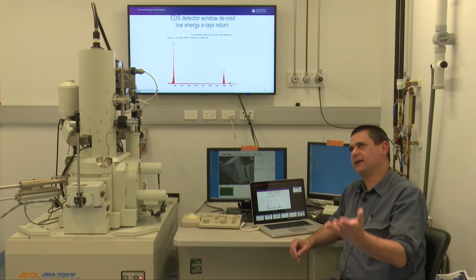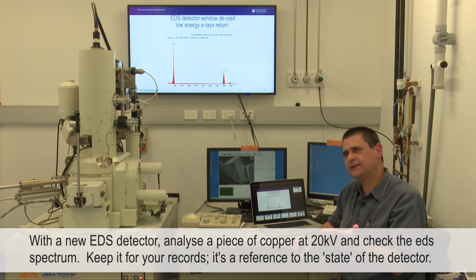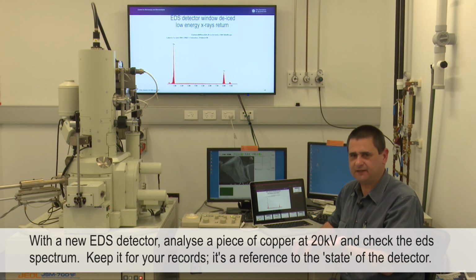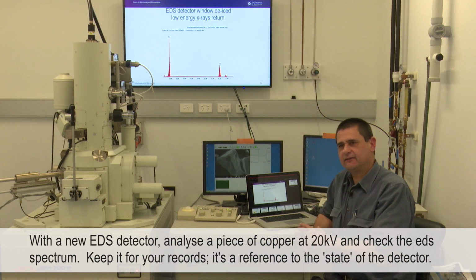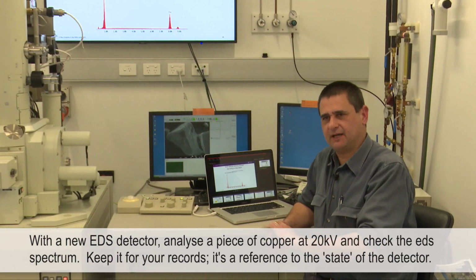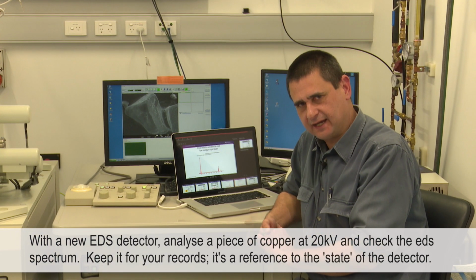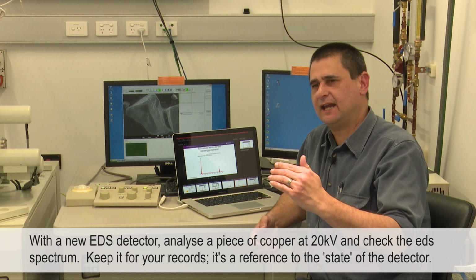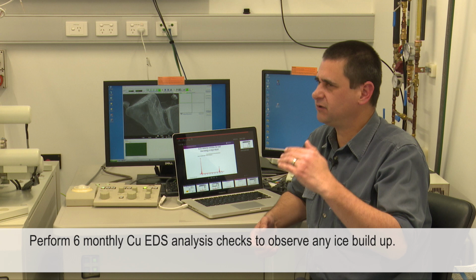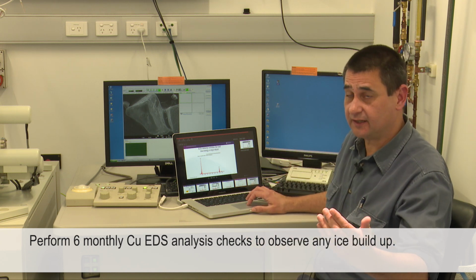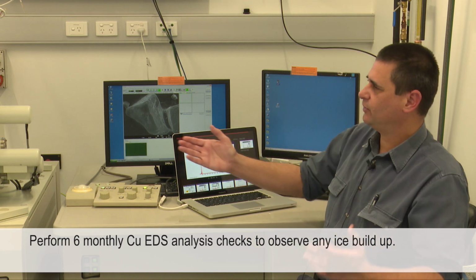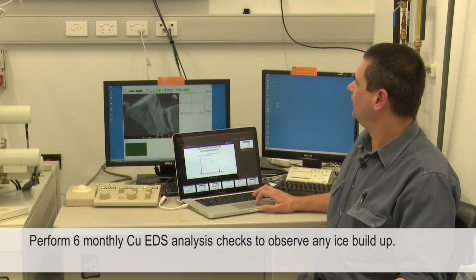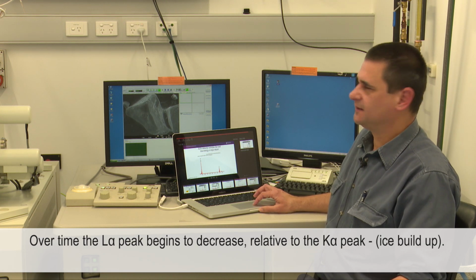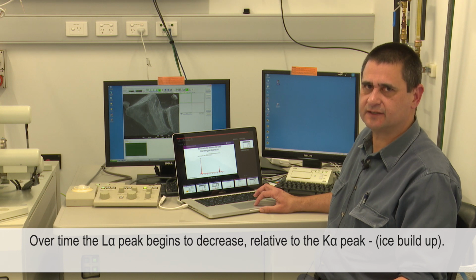If you ever end up buying an SEM with an EDS detector, one of the things I first do when I get it straight away is I just put a piece of copper in there. A piece of wire will do, and I grab a copper spectrum at 20 kV, and I just keep that, and then I reference it, and then every 6 months or every year I grab another copper K alpha spectrum. And you'll probably notice, depending on the SEM, depending on the detector, depending on whether you have an antechamber or not, but over time the L peak begins to decrease relative to the K peak.